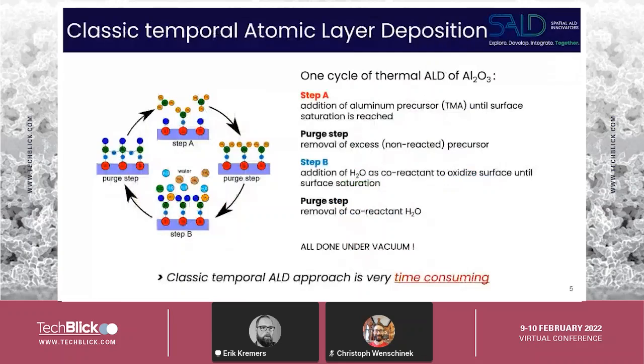I want to talk a little about ALD because I'm not sure everyone is familiar with it. ALD is a very simple technology — at least that's what we say — but in the end it's the alternate exposure of a substrate to a certain gas to start a chemical reaction on the surface. That's done by putting a substrate in a vacuum chamber, going to a very low pressure level, and then releasing precursor A into the vacuum chamber. In this example it's TMA, which is an aluminium precursor. When the whole chamber is saturated with the precursor vapor, the surface of the substrate will also be saturated, and at that point all remaining...